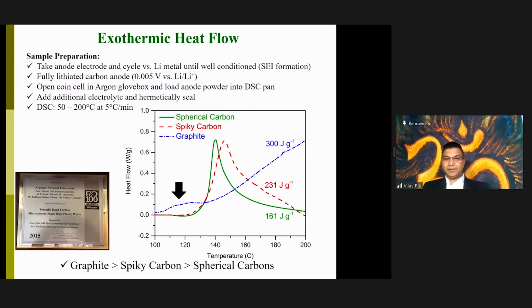The spherical carbon generates some heat during the overcharging and thermal runaway of the battery, which is a small number compared to your graphite that is sitting today in your cell phone. So that heat generation in graphite is very high, almost double, up to 200 degrees Celsius. This convinces that this can make the battery really safer, where the material is used in a sustainable way. This technology won an R&D 100 award in 2015. Namely, they choose only 100 technologies around the globe to figure out which are the best for that particular year. And this technology was chosen based on that.